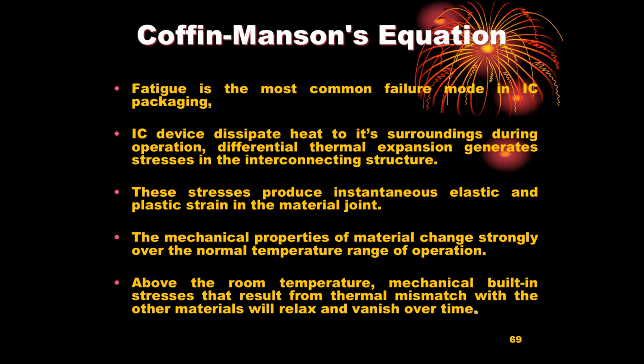These stresses produce instantaneous elastic and plastic strains in the material joint. As the mechanical properties of the material change strongly over the normal temperature range of operation, the room temperature mechanical built-in stresses that result from thermal mismatch, especially with the other materials, will relax and vanish over time. That's one good and bad aspect.